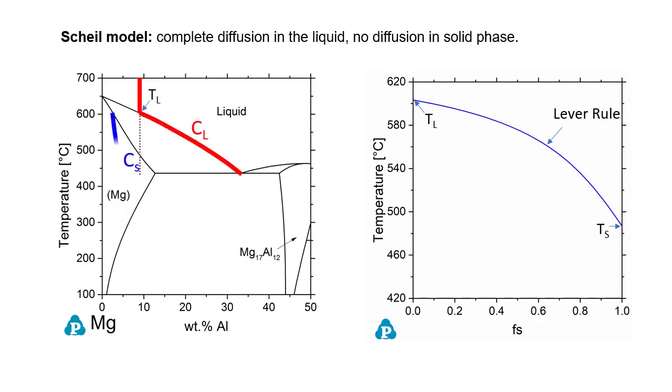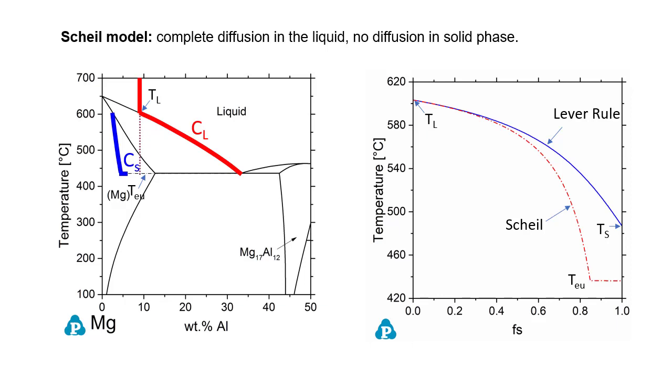While the overall composition of the solid phase will move away from the equilibrium solidus line and follow the blue line, this is because the solids formed at higher temperatures contain fewer solute element. In addition, the solute element will be enriched in the remaining liquid, thus lowering the liquidus temperature. Usually the solidification process finishes when the eutectic reaction is reached. The temperature versus solid fraction curve is shown as the red line. We want to point out that although simple binary and ternary systems are often used as examples to demonstrate the functionality of the Pandat software, Pandat software is much more powerful and can be readily used for simulations of multi-component alloys containing more than 10 components.